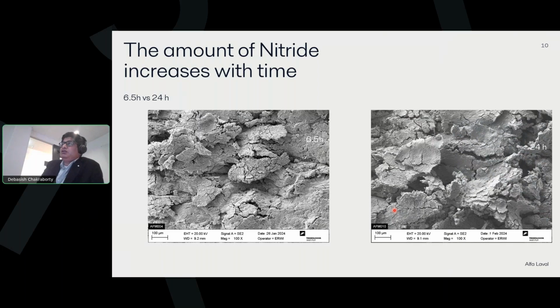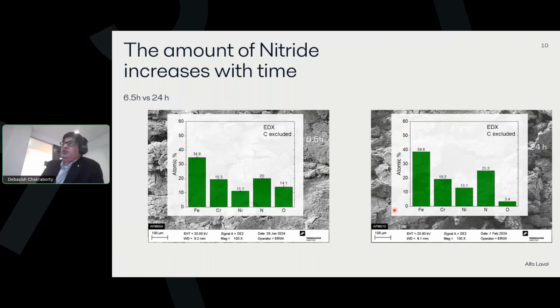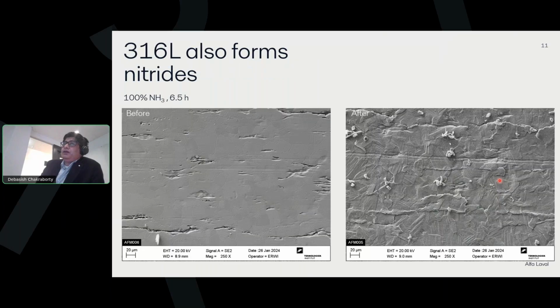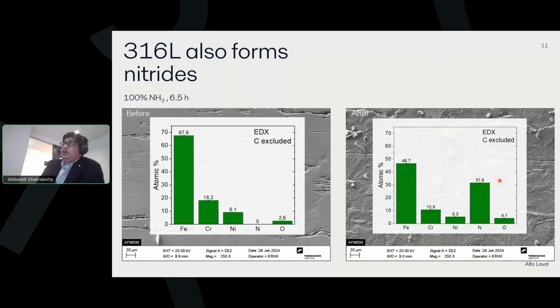If you see what happens when the exposure time increases, you see more nitride forming. The amount of nitrogen increases, and this is just 24 hours. And we're talking about 20,000 hours or 10,000 hours of durability, right? So it's really challenging. And then this is 316L. After treatment it looks not as bad as 310 visually, but you see a lot of nitrogen still. So nitride is forming, and the chromium oxide layer is gone.